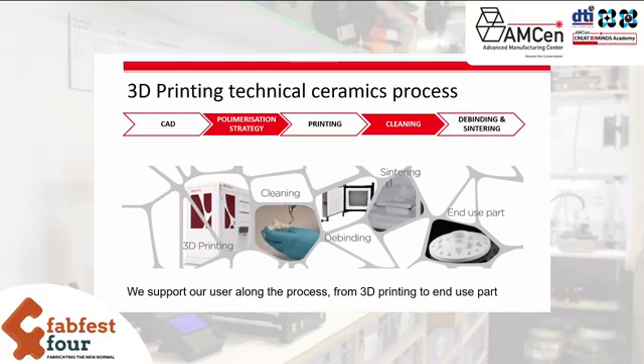So after printing, the part is made with a mix of ceramic powder and polymerized binder. This is why we have to do two thermal treatments. First one, debinding, in order to burn the binder, and then sintering in order to close the porosity and to densify the ceramic. It is during the sintering process that we have some shrinkage, between 10 and 20%. And the shrinkage only depends on the chemistry of the formulation.